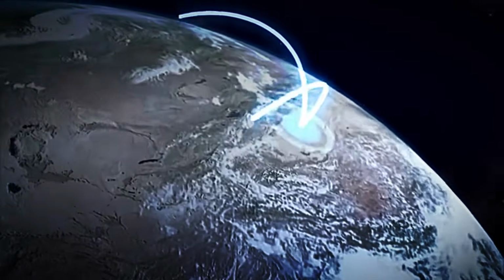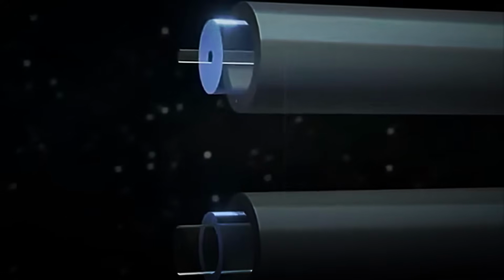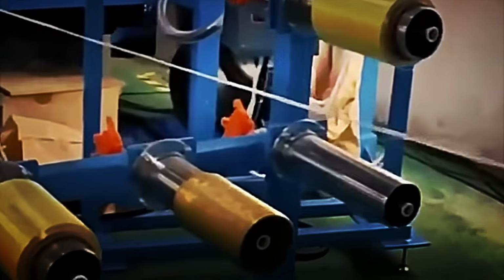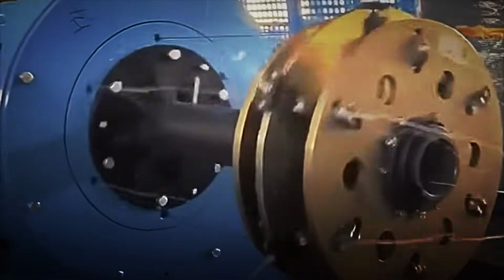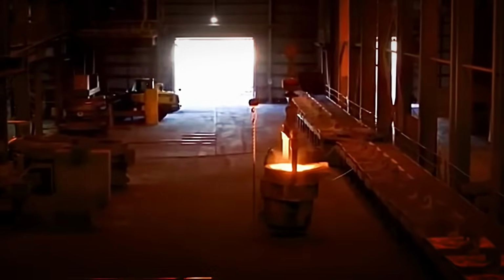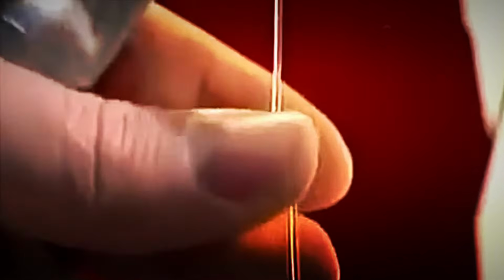This cylindrical structure will serve as the mold from which kilometers of optical fiber will be extracted. This phase involves working not with sand or powder, but with a hollow glass tube that acts as the initial support. The tube is mounted on a rotating machine that spins it at a constant speed, while a stream of reactive gases derived from silicon and germanium is introduced. A high-intensity flame heats the tube to over 1,500 degrees Celsius. When the gases come into contact with the incandescent wall, they react and precipitate as tiny glass particles that adhere to the inside of the tube. Each rotation deposits another layer. Over time, the interior is coated with a uniform, extremely pure glassy material.